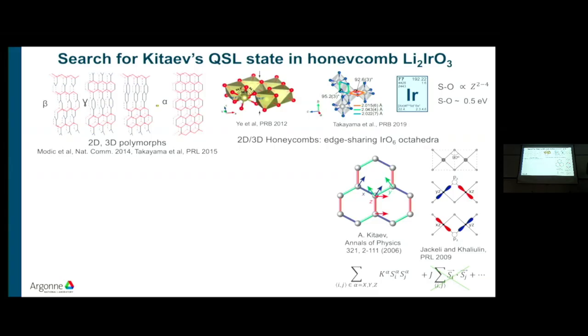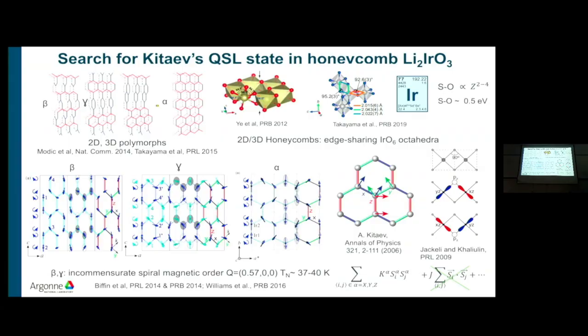These are not regular octahedra, so this cancellation doesn't quite happen. And then you end up with magnetic order, but quite complex magnetic order, spiral magnetic order where the spins curl around, and that is because this Kitaev exchange is quite significant. And if you look carefully here, you see some bonds where the spins kind of want to go perpendicular, but they really can't because the structural motif is not perfect.